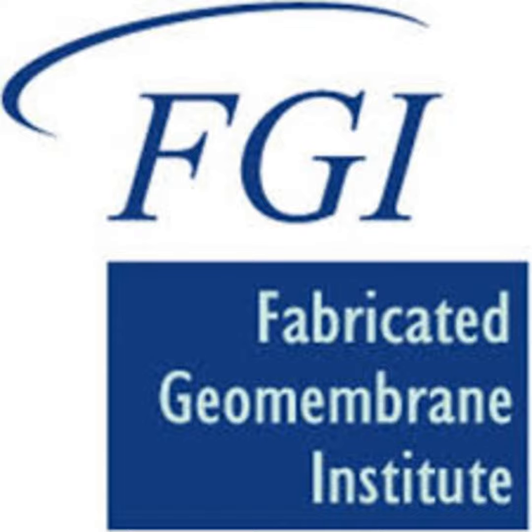But other than that paper, I don't really recall seeing the large displacement shear strength of a hydrated GCL come up in design. On the other hand, the difference between the peak and large displacement shear strength for the interface is considerably less, and also you need less displacement to achieve that. So if your design could tolerate those larger deformations, I could see that being a reasonable design strength to go on. Those are my thoughts.